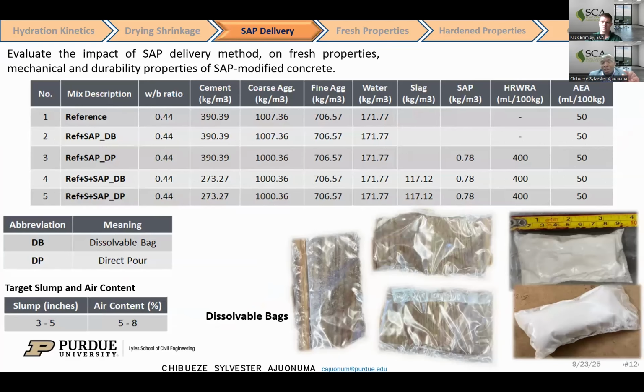For the mix design that we used for the lab-scale experiments, we designed 5 concrete mixes at a constant water-to-cement ratio of 0.44. We are trying to evaluate how effective the dissolvable bag that we brought on board is at dispersing SAP, and how effective it is for internal curing purposes.